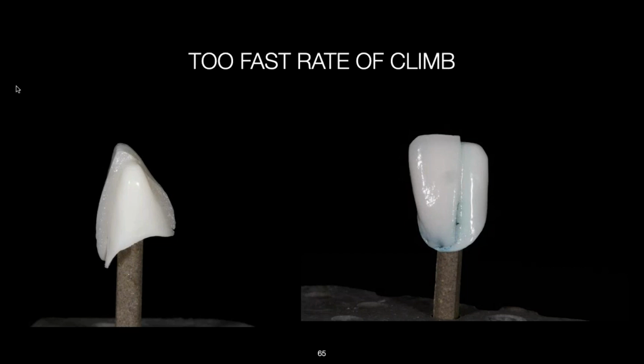So just to let you know, you have to be really careful when you do this. Remember, the zirconia takes a long time to heat up, really a long time. And especially if you put the putty inside the pegs, that doesn't help either to heat it quicker. So when you have a little coping, it's not even as bad as if you have a big crown, where you have to get that zirconia hot enough so that when that VM9 or Lumex starts to turn into glass, it can wet the surface. If you don't preheat it enough, that would be 400 for about 6 or 7 minutes.